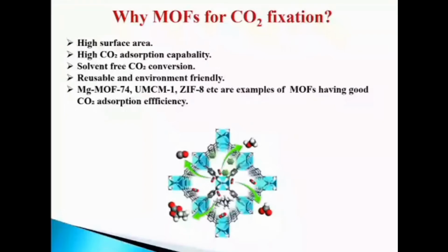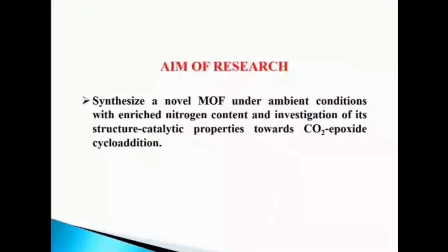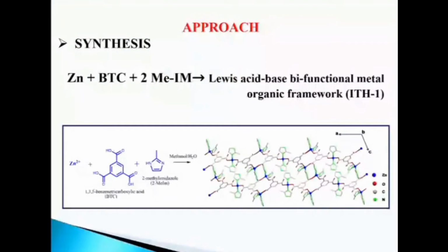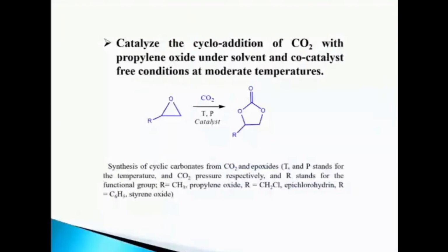Our aim of research is to synthesize a novel MOF under ambient conditions with enriched nitrogen content and investigate its structural and catalytic properties through carbon dioxide epoxide cycloaddition. Approach: first is the synthesis of our MOF at room temperature by precipitation method. For this we use zinc nitrate hexahydrate, benzene tricarboxylic acid, and 2-methyl imidazole, which gives a Lewis acid-base bifunctional metal organic framework, that is ITH1. This figure represents the synthesis of our MOF. Next is catalysis, that is, catalyzing the cycloaddition of carbon dioxide with propylene oxide under solvent and co-catalyst-free conditions at moderate temperature. Let us move on to results and discussion.